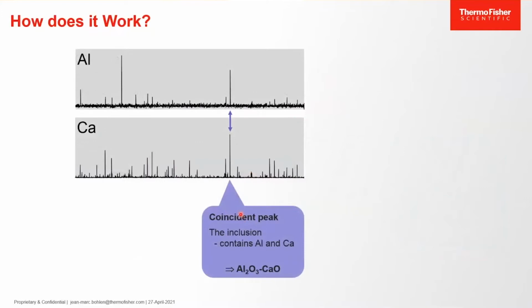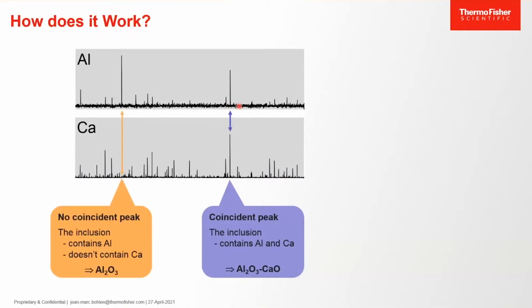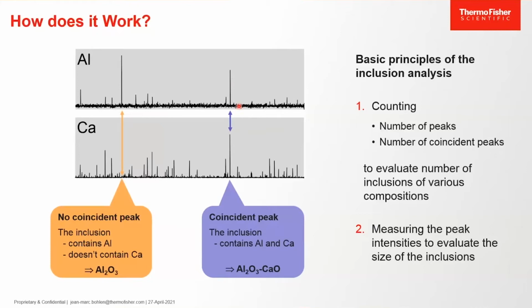On this other slide, the run chart of the element calcium has been added. When a coincidence of an aluminum peak with a calcium peak, like here, is observed, it signifies that the inclusion contains both aluminum and calcium. The inclusion is therefore likely a calcium aluminate. When no coincident peak exists on the calcium channel, it signifies that the inclusion contains aluminum but no calcium. In this case, the inclusion is likely an aluminum oxide. So these are the basic principles of the inclusion analysis, where we count the number of peaks and number of coincident peaks in order to evaluate the number of inclusions and their compositions. And second, we measure the peak intensities to evaluate the size of the inclusions.